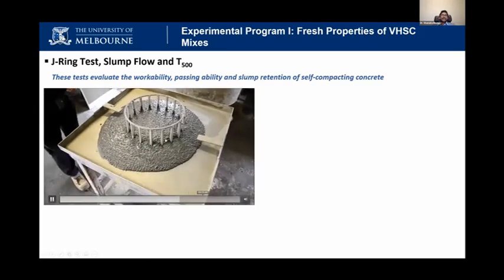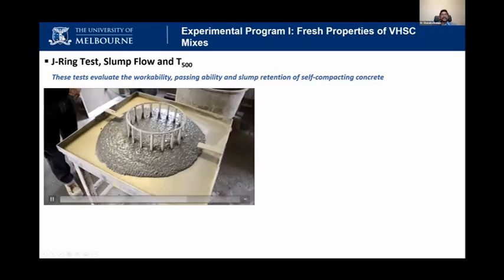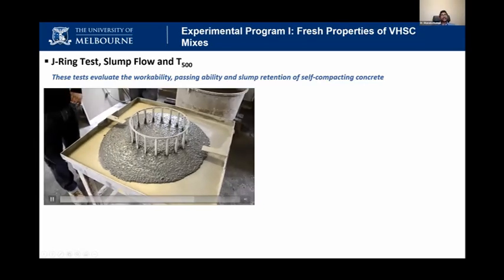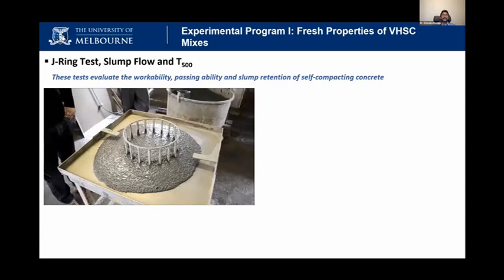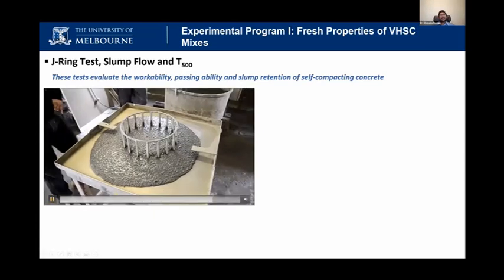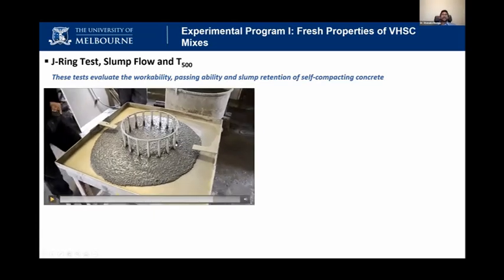This is a J-ring test that evaluates the workability, passing ability, and the slump retention of the self-compacting concrete. The workability is measured by the diameter of the spread. Passing ability is measured by the concrete going through the reinforcement. That shows how the concrete can go through the reinforcement. And the slump retention is measured after 3 hours.